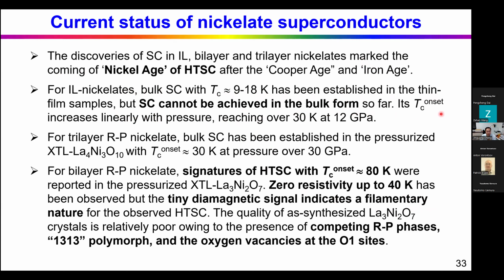Its onset temperature increases linearly with pressure and can reach about 30 Kelvin at 12 GPa. For the trilayer nickelate, bulk superconductivity has been established under pressure with the TC onset about 30 Kelvin at pressures over 30 gigapascal. For the bilayer nickelate, signatures of high TC superconductivity with TC onset of 80 Kelvin were reported in the pressurized single crystal, and zero resistivity up to 40 Kelvin has been observed, but the tiny diamagnetic signal indicated a filamentary nature for the observed superconductivity.